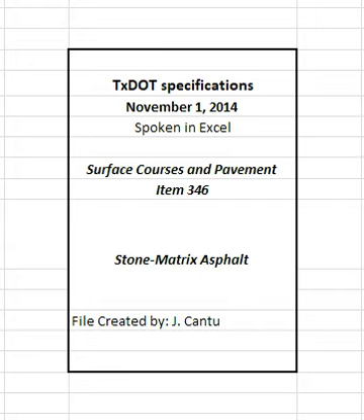4.7.1 Weather conditions. 4.7.1.1 When using a thermal imaging system, the contractor may pave any time the roadway is dry and the roadway surface temperature is at least 50 degrees Fahrenheit. However, the engineer may restrict the contractor from paving surface mixtures if the ambient temperature is likely to drop below 32 degrees Fahrenheit within 12 HR of paving.